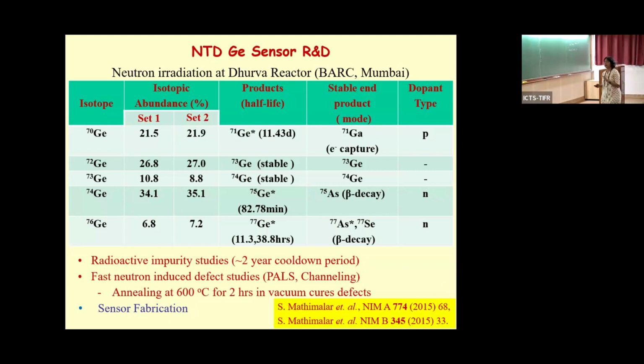Because of that, you have made the sensor where you can control the R. What will happen if I don't dope it? If I have a pure semiconductor, as you cool down, the resistance becomes too high. So with doping, you are bringing the resistance into the measurable region. If I put a very high concentration, like 10^19 per cc carrier density, then it will become metallic. And if I have less than 10^16, then it still is not in a measurable range. So you have to achieve this level of doping, which cannot easily be done chemically, but you do it with neutron transmutation.